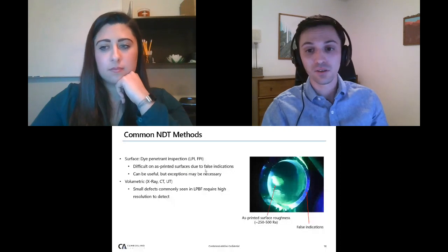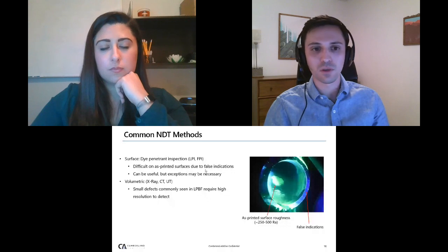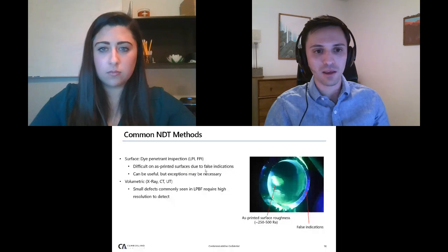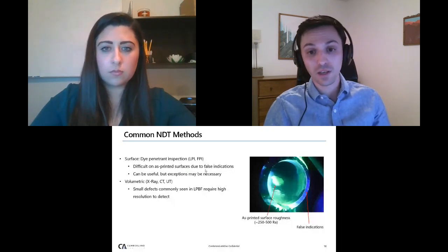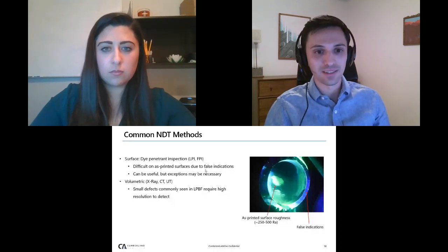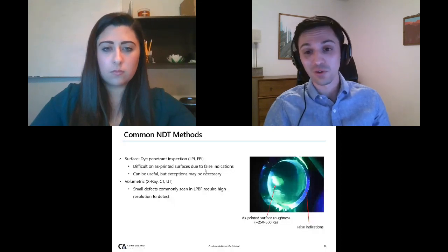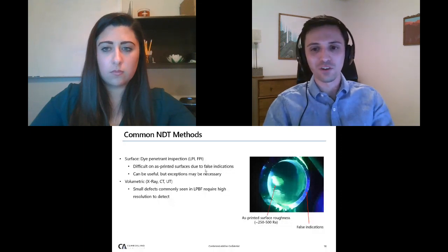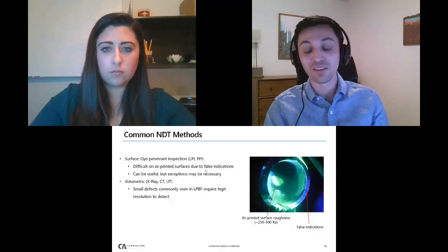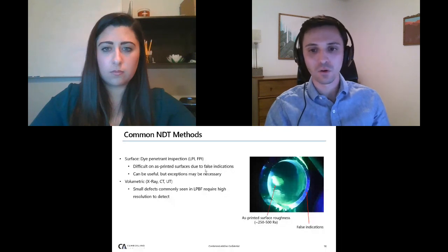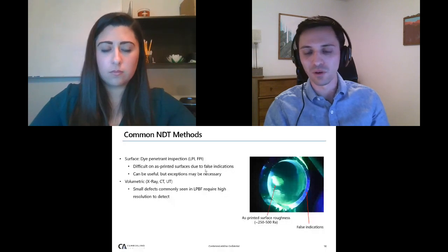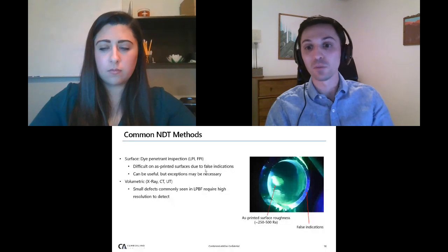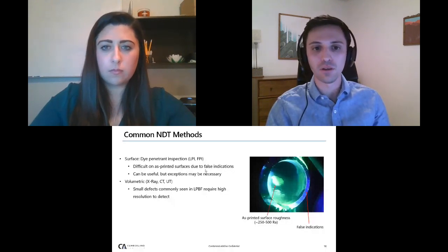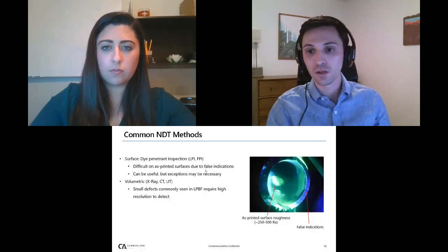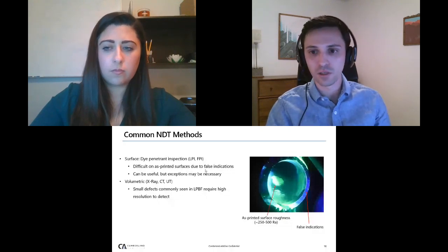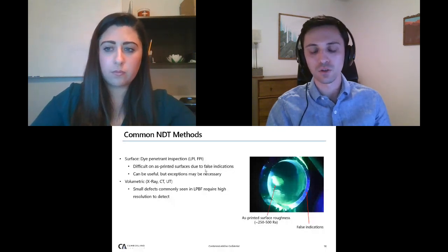So common NDT methods seen, and this isn't just AM, for all kinds of metal parts, are dye penetrant inspection, so LPI, FPI. Dye penetrant, you can get useful data out of that for AM parts, but you should expect a lot of false indications. So things are going to glow that aren't actually a problem. The image on the right is a dye penetrant where all the glowing, colorful bits are false indications, or things that were later deemed not a problem. That big glob is a surface roughness spot somewhere in the range of 250 or 500 RA, because that's an as-printed surface. Now, if this part was machined, it would appear in an FPI just like any other machined part. But this part hasn't had extensive surface finishing, and so as a result, you get these indications that are showing up in the surface roughness.